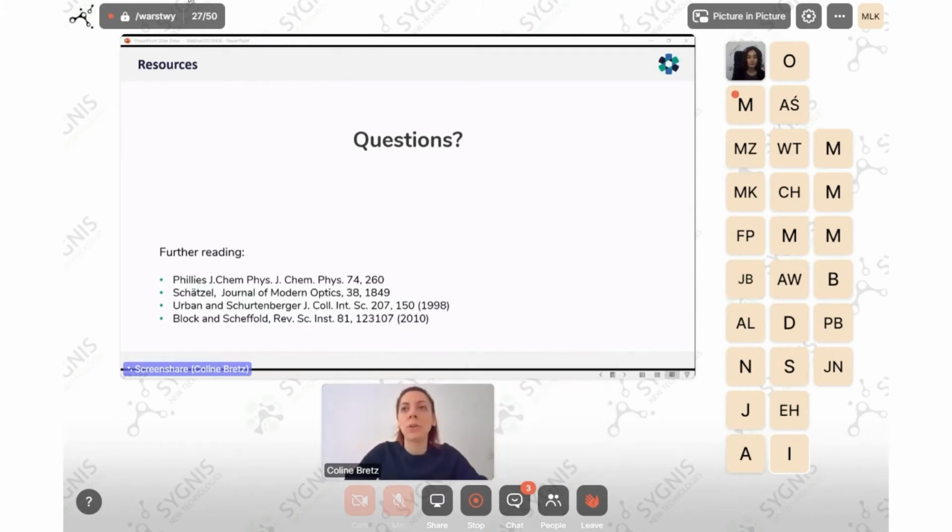So typically, when we use this switching, it's extremely fast. We're talking about something like 800 nanoseconds of switching time. So typically, the dynamics that we will see are the same. The sample does not decay fast enough for us to consider it not the same scattering volume. So we don't have a problem in this case because the switching is extremely fast. Okay, I get this approximation. Thank you. No problem.